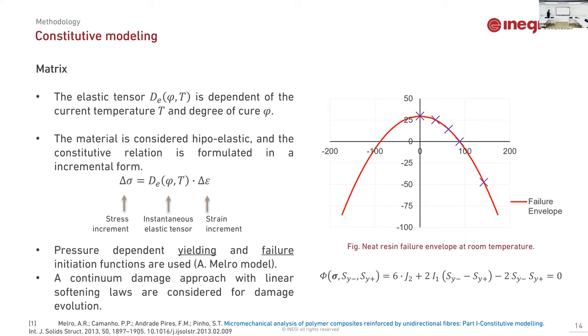How was it considered? The resin is a polymer and the material has a pressure-dependent behavior. So I have used the model proposed by A. Melro, which is a pressure-dependent constitutive model to predict the yielding initiation and also the failure initiation if I change the yielding stress by the failure stress. This is the equation that is commonly used. And after that, when the failure of the resin is achieved, I have also introduced a continuum damage model to simulate the damage evolution and model the crack propagation in the resin.